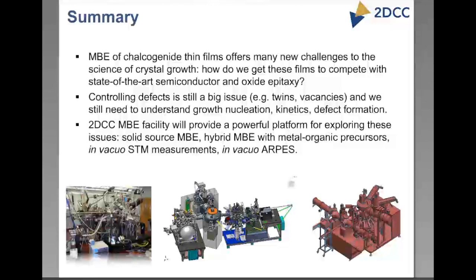We're talking about that buffer layer engineering where they deposited the low temperature bismuth selenide. What is the role of that? The question here was, I gave the example of Seong-Shi Ko's engineered buffer layer, and the question is, what is the role of that buffer? From what I understood from the paper, I haven't really talked to Sean about this, the indium selenide itself gives you a really good surface to grow bismuth selenide on top of. But they can't grow the indium selenide directly on sapphire for some reason. There's some funny chemistry that occurs there.